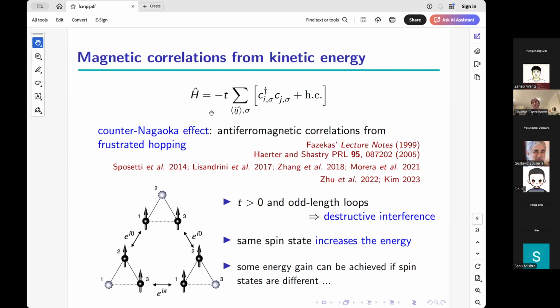But of course, in this case, if we have what is known as a positive overlap integral, so T is positive and we have a minus T in the Hamiltonian, then having an odd length loop means that the process picks up a factor minus T to the 3, minus t cube, which is negative, and you have perfect destructive interference. So the ideal case for a square lattice that led to the minimal energy of a ferromagnetic configuration is here quite bad for the system, because the hole hopping around the triangle cannot take advantage of the kinetic energy at all. It leads to destructive interference and the process doesn't gain any energy.